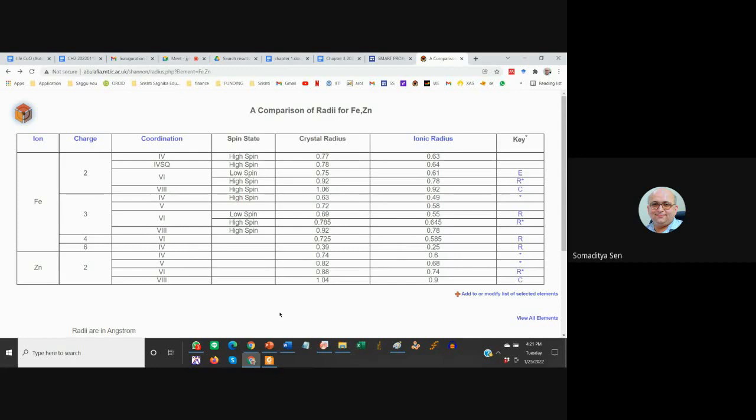On the other hand, it can lose one zinc for two iron substitute atoms. In that way, you have compensated the extra positive charge. So by doping something which is not of the same charge and not of the same dimension, you have generated some stress, strain, or defect states in the crystal lattice.